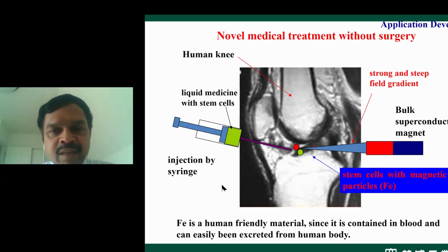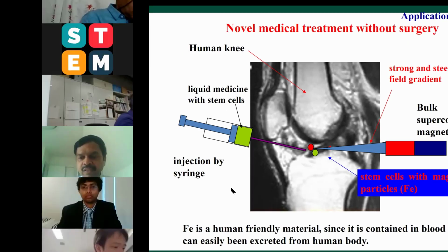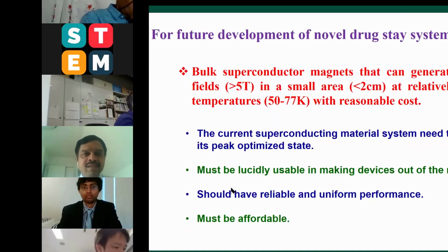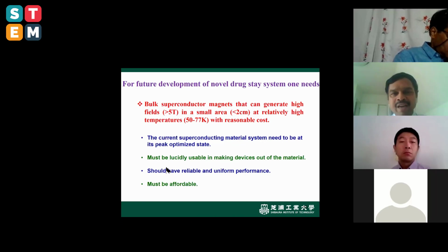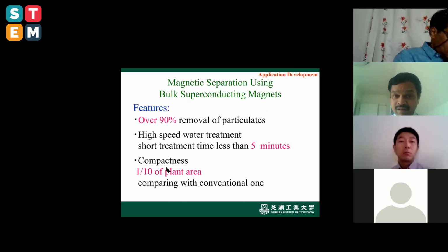Here also the same thing. Stem cells with magnetic particles will be injected by syringe, with the bulk superconducting magnet outside at around 5 Tesla. But in this case, we always need a bulk superconductor that generates a high magnetic field of more than 5 Tesla over a small area like 2 centimeters. In that, our PhD students and master students are working to develop stronger magnets to work at around 77 Kelvin.